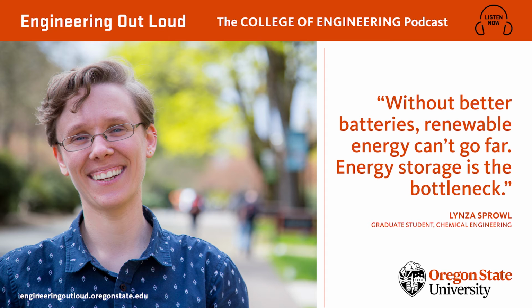You can't stop it from breaking down, but you can add different organic solvents that break down differently, and so you can kind of control what products go into this barrier. So basically, you want to engineer an electrolyte that will break down to form a barrier that lithium ions can still get through. You want a barrier which is ionically conductive so that the lithium ions can diffuse through and reach the anode. If the electrolyte solvent breaks down differently, you can make a more ionically insulative barrier which doesn't allow lithium ions, or can be more conductive to allow lithium ions.